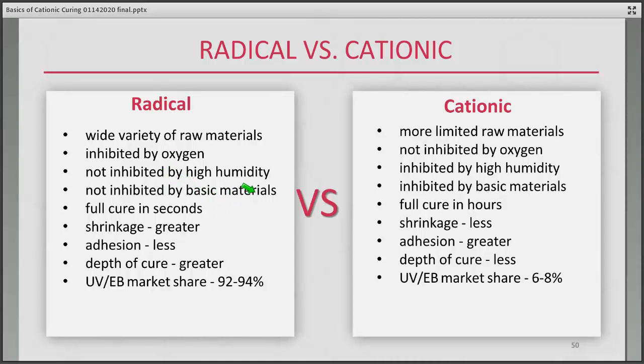Radical chemistry is not inhibited by basic materials. In fact, there are amines, for example, or acrylated amines that are used in radical cure. Cationic, you can't use basic materials. It will just kill the reaction completely with your acid catalyst, the acid photoinitiator. Radical chemistry, you get full cure in seconds, where cationic may take hours. You'll get your initial properties locked in, but to get the final properties may take hours. And in many cases, that really doesn't matter.